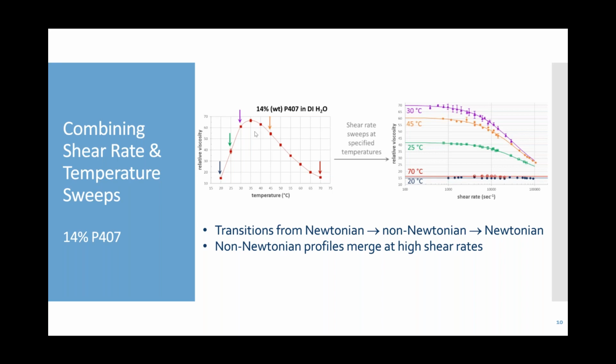Then ultimately, as you keep increasing the temperature, what tends to happen in these aqueous systems is you lose some of the hydrogen bonding, which really enhances the solubility of these molecules. So these micelles can start to collapse somewhat more, and then we see a drop in the viscosity. So we're seeing swelling with temperature and then a drop in viscosity coming from those molecules starting to collapse and become more condensed. This can be a general way of viewing what is happening with the structure to give rise to these types of viscosity behavior.